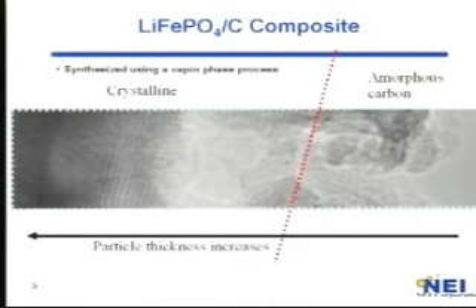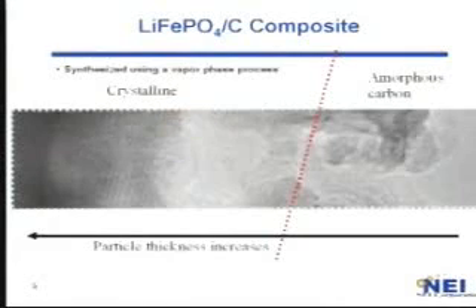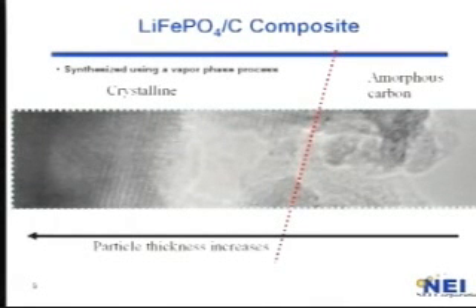At the beginning, we also had the same thought process: that we can produce the lithium iron phosphate and then coat carbon on the surface of each particle so that we can make this novel composite. However, the process is pretty tedious and it makes things very expensive. But here, just to show the TEM micrograph, you can see the lattice fringes from lithium iron phosphate, and you can see the amorphous carbon which has been coated by a vapor phase process. And the thickness of this coating is around 10 nanometers.